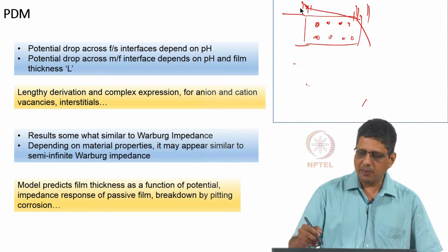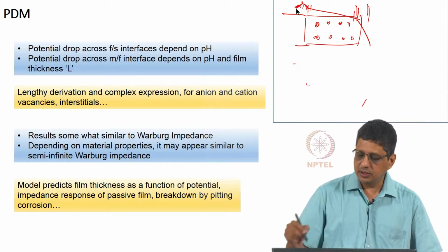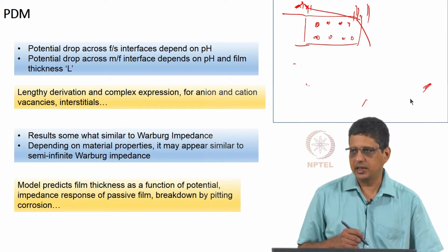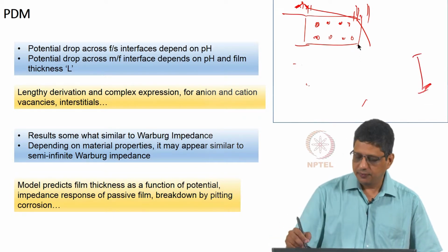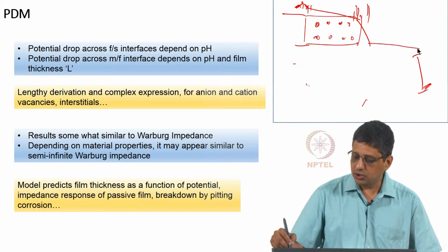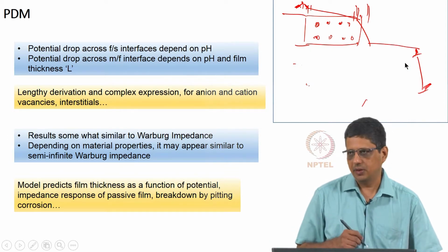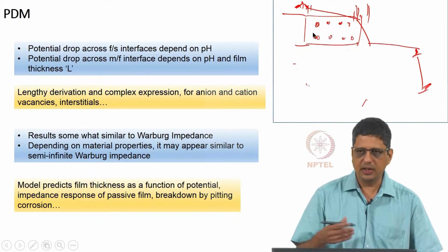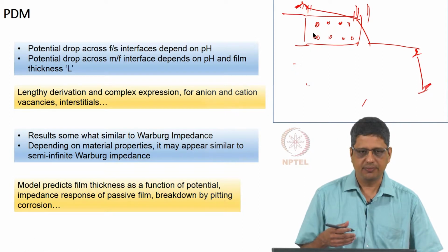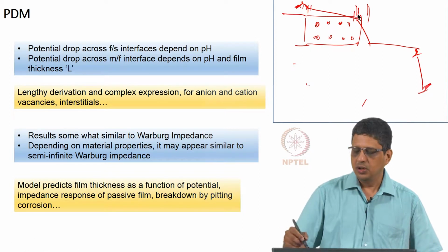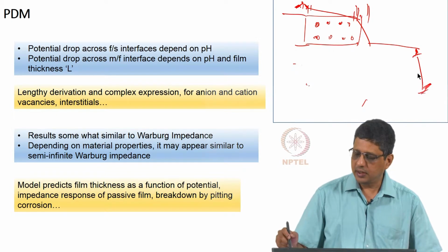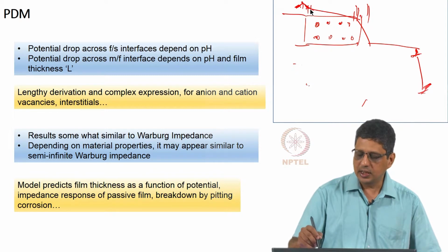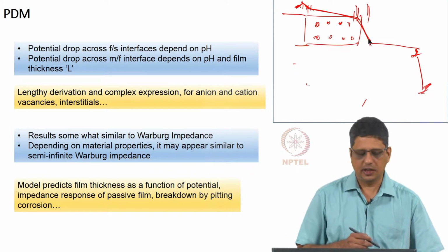So, what we apply is from this location to the other location in the reference electrode, and there we assume it is fixed anyway. In these calculations we are going to assume solution resistance is not that high, and the resistance due to the film is usually much larger. When we look at the potential drop across the electrode, measured with respect to a particular reference electrode, we have to consider 1, 2, 3 potential drops.